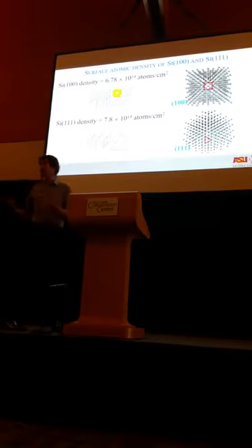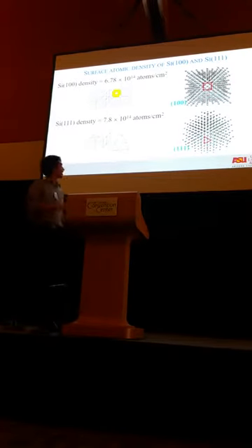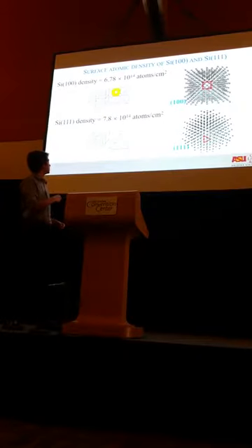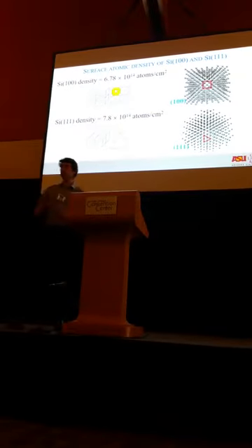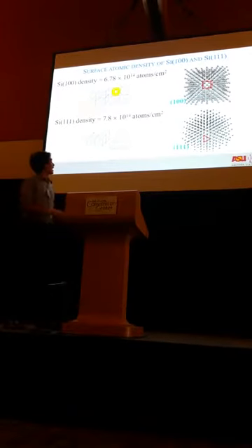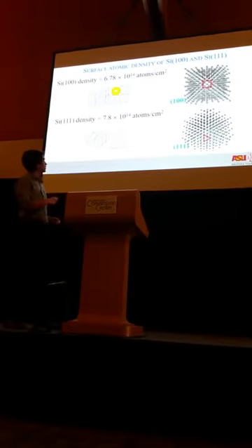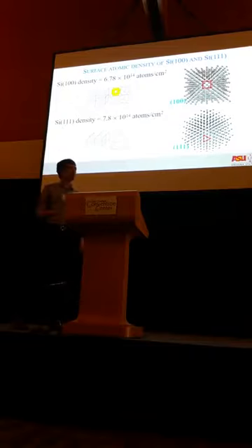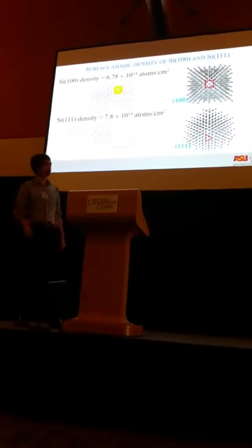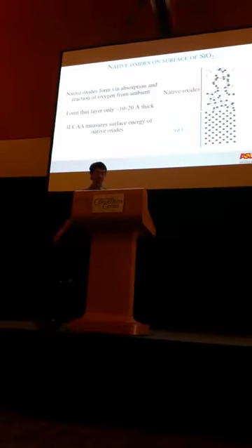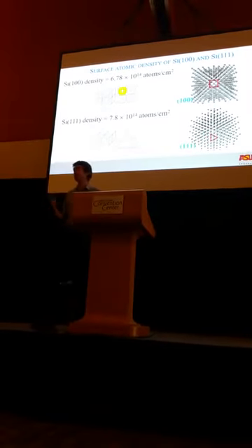We can see down here that silicon 111 has a very different orientation. The corresponding vector is normal to the diagonal cross-section of the cubic silicon crystal, and this orientation gives us a very different surface atomic density of about 7.8 times 10 to the 14 atoms per centimeter squared, which is about 15% larger than that of silicon 100.